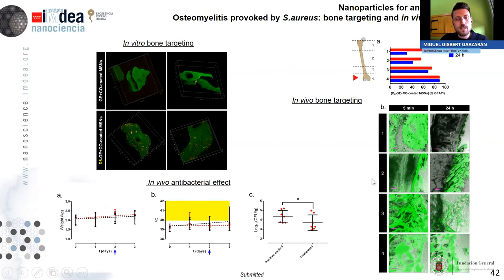So finally, we tested the in vivo antibacterial effect. Let's look at this one. We can observe that the nanoparticles, the combination of the nanoparticles loaded with either moxifloxacin or rifampicin, were able to decrease the number of bacteria. So in the end, we can conclude that this might be a promising strategy to deal with a hard-to-treat disease